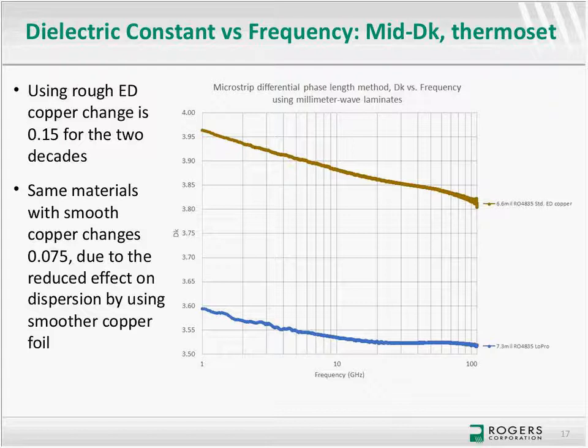And look at some of the materials with thermoset. You can see here one of the things that I want to point out is that besides the impact on the loss of rough copper is what happens to the dielectric constant change, the slope of this curve, when you're comparing a smooth copper foil with one that has a rougher copper foil. So you see the same material actually displays what we call an apparent constant difference because of the impact of roughness on the phase velocity of that signal, and how that translates into an effective dielectric constant.